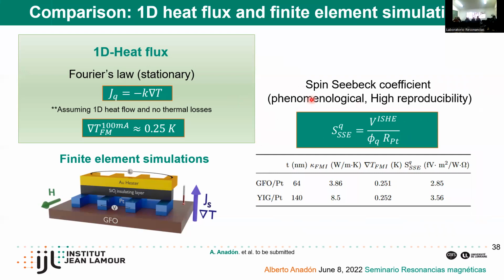And to do this, we introduce this spin-Seebeck coefficient, which is basically the voltage coming from the inverse spin Hall effect normalized by the heat flux and the resistance of our detecting layer. And if we compare this in both systems, we see that the spin current generation is mostly similar in both systems. So basically, we are introducing to the community this new ferromagnetic insulator material with magnetoelectric properties, which is able to generate spin current mostly as good as yttrium iron garnet.